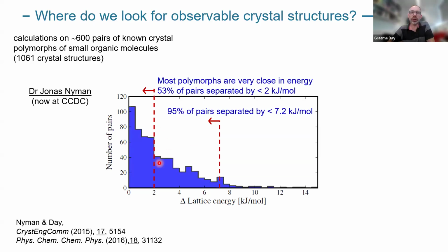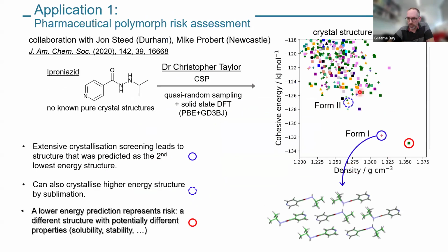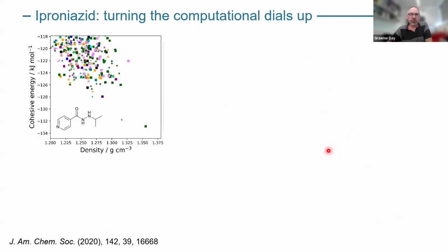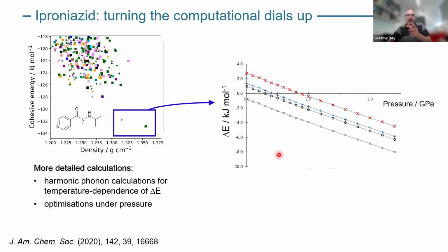What Jonas found was that over half of polymorph pairs are separated by really small energy differences, less than 2 kilojoules per mole. And almost all polymorph pairs are separated by just over 7 kilojoules per mole. So you usually just have to look for that range. If we look back at our landscape, this is where all of those 2 observed structures are sitting within about 7 kilojoules per mole. But again, this one worries us. So computationally, what we did were a few things.